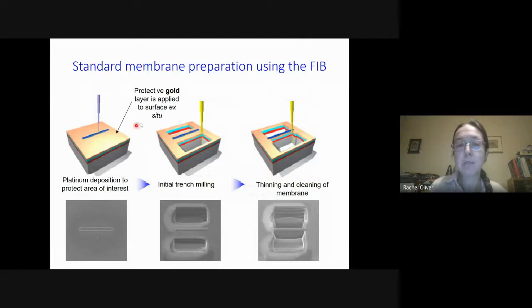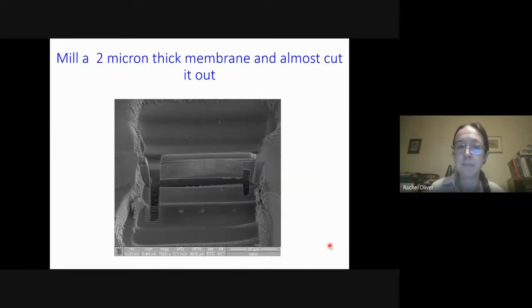And when we want to prepare a transmission electron microscopy sample, what we do is put a platinum layer over a region that we're interested in. So this is the deposition of material in the focused ion beam. And then we use the ion beam to dig 2 really big trenches either side of that metal strap. And we thin down to form a membrane. Now, that was something that was established before we started trying to do atom probe. So that's exactly what we did as a starting point for making our atom probe specimens.